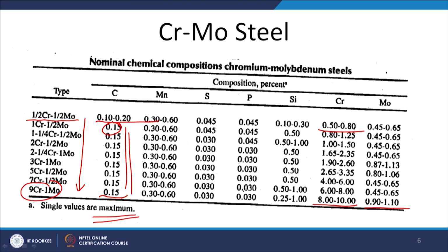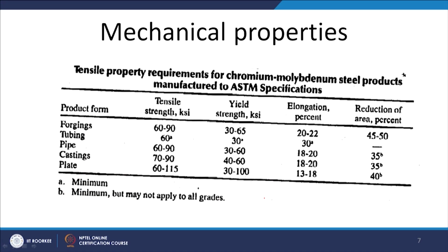Wherever a range is given, it shows the allowable range for that particular element, like the maximum allowed value of sulfur and phosphorus. These are values like 0.03 or 0.045% in order to avoid the solidification cracking tendency of the weld joints. Since, as I have said, these steels are used at a higher temperature, they offer quite good ductility and very good strength. As per the form of the steel, we have a very wide range. These chromium molybdenum steels have ultimate strength in the range of say 60 to 115 KSI, and in case of yield strength it is 30 to 100 KSI, elongation is 13 to 18 percent. So, these have quite a good combination of strength and ductility.